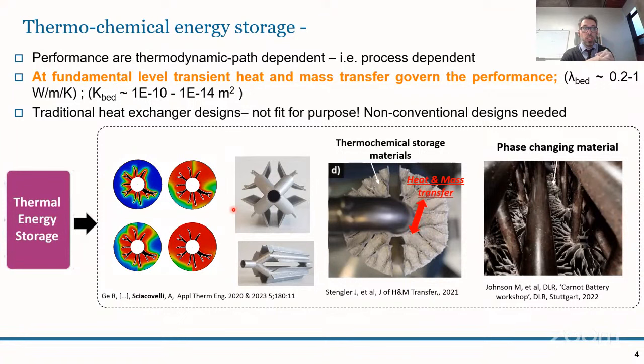mass transport processes. What you see here at the center, from the literature, is how a thermochemical storage material looks like. This is strontium bromide, and the challenges are typically underpinned by the low thermal conductivity of this material, as well as usually low porosity of this bed, which essentially slows down transfer of heat and of mass, particularly of the sorbate that is in contact with this material that triggers the reaction. In this case, it's a reversible reaction between strontium bromide and water vapor.